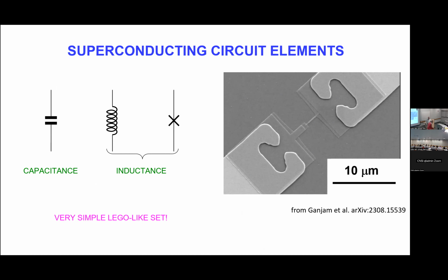It's improved contact with the substrate. Yes, the contact with the substrate, but also probably the defects along the edges, which can be removed by a much more aggressive processing that this particular method favors. So it's more that this method improves the process, though it also has nice properties. For instance, it has a very good oxide, which probably helps. It's also chemically quite independent from the aluminum. So when you make this part of the circuit, you can remove some of the dielectric defects.